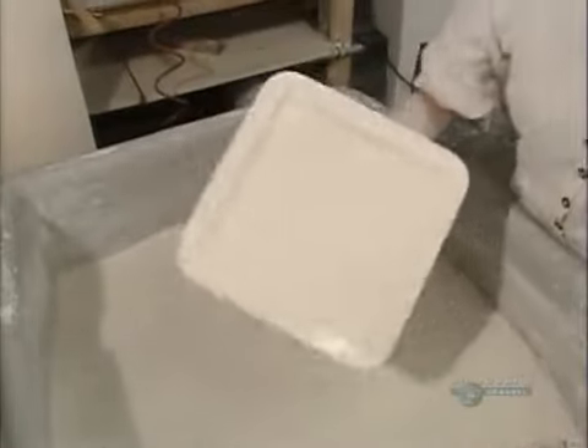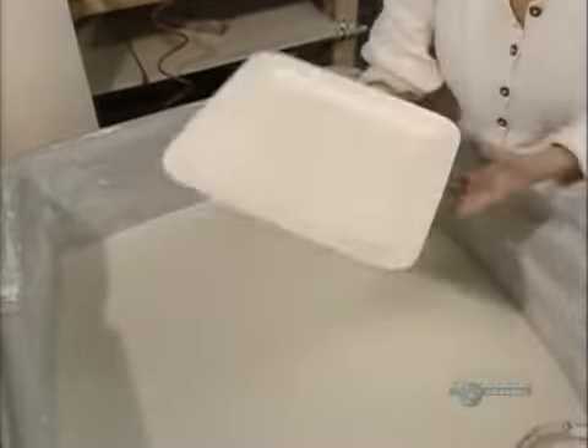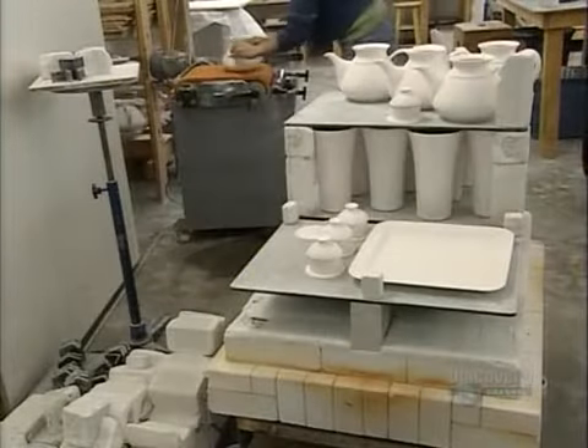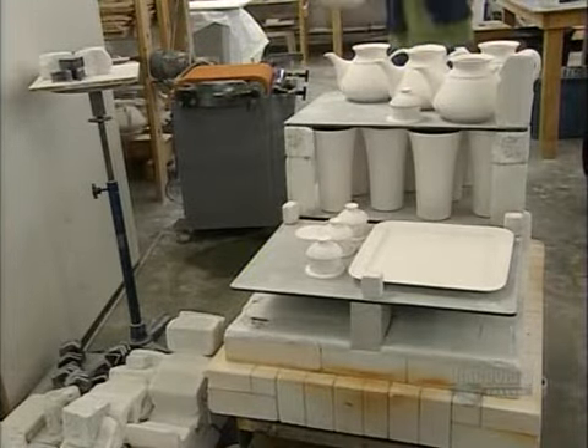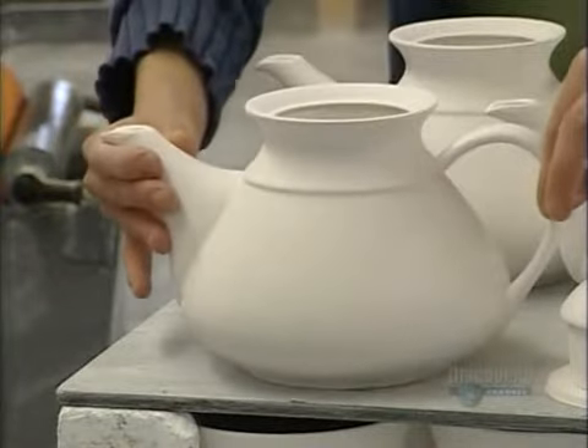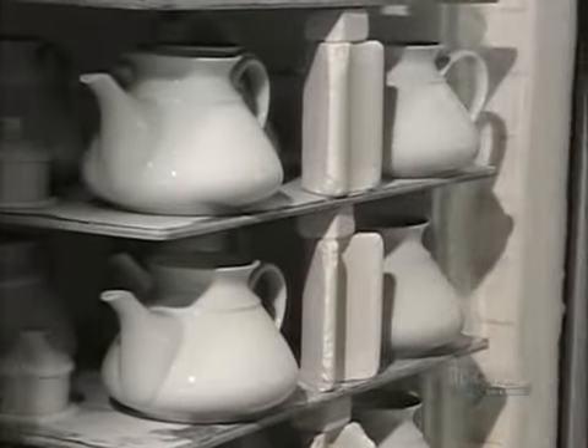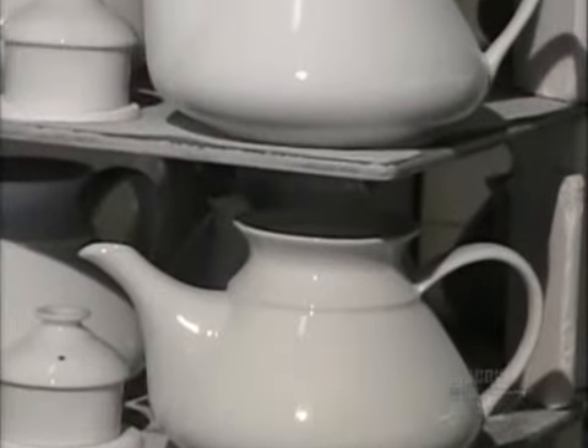In the second firing, they make the porcelain pure white by carefully controlling the air in the kiln. Reducing the oxygen level removes any undesirable colors. This time, the temperature is higher, 1,400 degrees Celsius. It shrinks the pieces by about 15%.